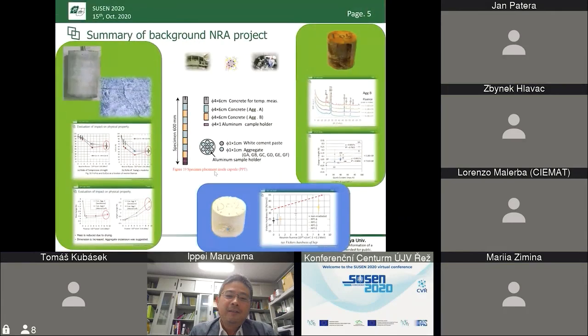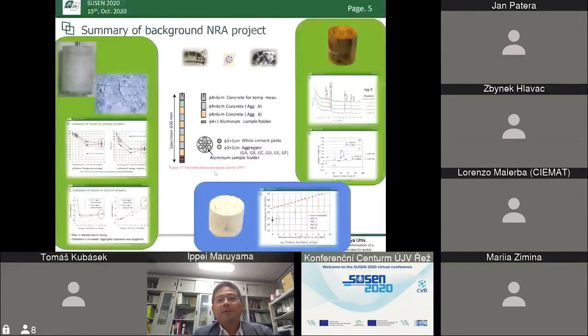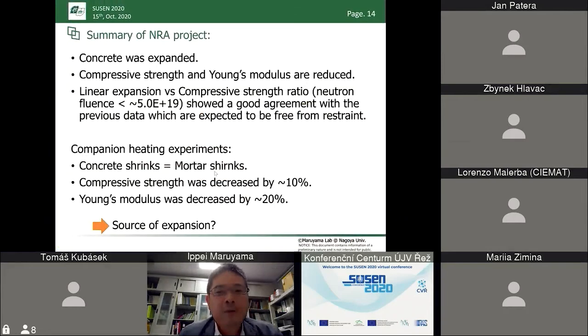Well, so the summary of the Nuclear Regulation Authority project: we found that the concrete is sensitive to the neutron irradiation process, and the compressive strength and the Young's modulus are reduced. And the linear expansion versus compressive strength ratio showed a good agreement with the previous data, which I didn't show today, which correspond to the degradation of concrete with free deformation and not the restraint condition.